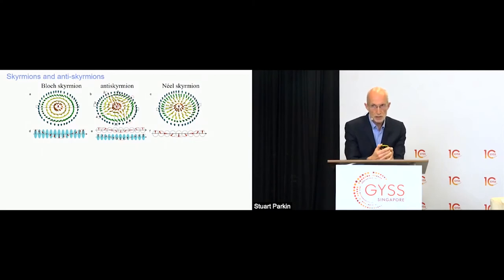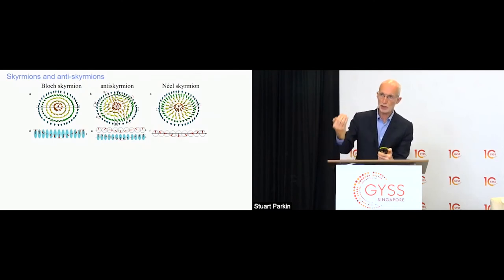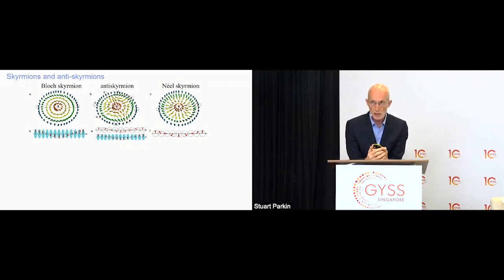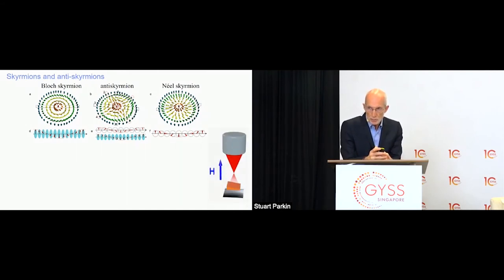However, it was theoretically predicted that in some systems with lower symmetry, you would, instead of seeing these two types of Bloch and Néel skyrmions, you could find what is called an anti-skyrmion. And in an anti-skyrmion, the structure of the boundary between the outer material magnetized up and the inner material magnetized down changes around the circumference between Néel and Bloch-like segments. And every time you go from a Néel to a Bloch-like segment, the chirality changes. And this object was theoretically predicted, but had never been observed until we first observed it 4 years ago. And I want to show you how we observed it. We observed it using Lorentz transmission electron microscopy.